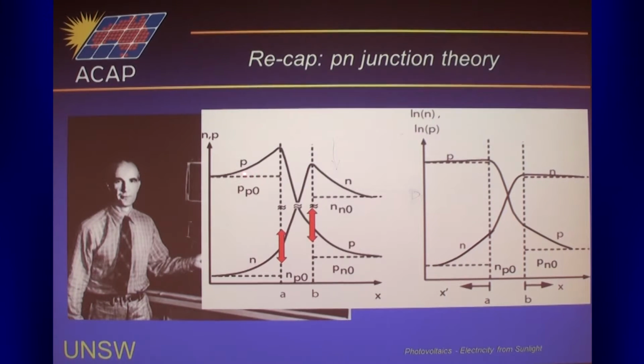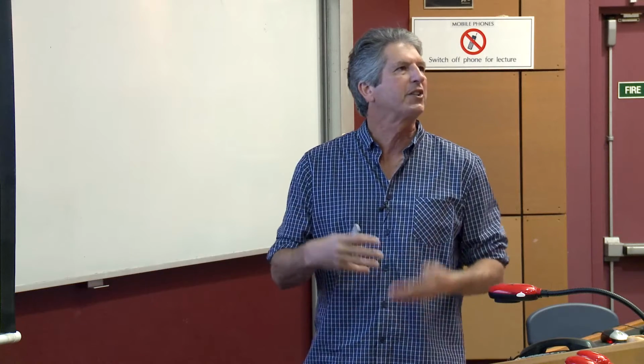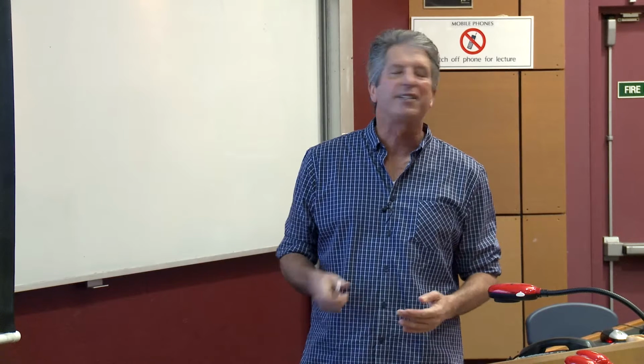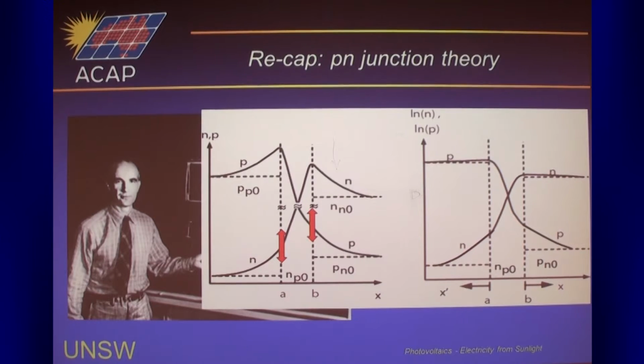If you go to heavier doping, like this side is heavier doped than this side in this case, you can suppress. This drawing's not all that good. This should actually be bigger than this. This drawing's more representative here, but the proportionate increase here is smaller than the proportionate increase in this case. So going to heavy doping sort of suppresses how high this concentration gets. The current flows depend on the gradient here. So dn/dx, if you call x this direction, minus dn/dx, determines how many electrons flow in that direction there. There's a constant, the diffusivity, D, that determines how much flow you get for a given gradient.